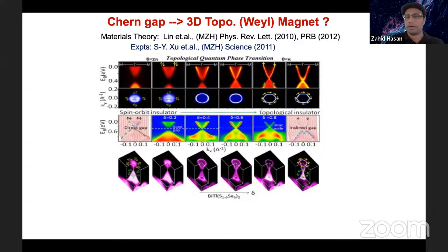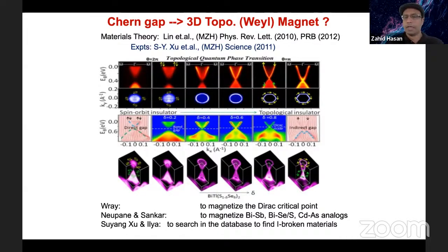So now that we know how to do a Chern gap or topological gap in magnets. Back in 2010-11, we were exploring a band inversion transition in a topological insulator. At the band inversion point, you have a 3D Dirac fermion, right? And when you magnetize a 3D Dirac fermion, as we know, it can only split into a pair of Weyl fermions. So we were trying to magnetize this Dirac critical point in a topological insulator system. But it turned out that magnetizing topological materials is a very tricky job. And even if you magnetize it, the gap may be small, ARPES may not be able to see it. So that was happening back then. We could not resolve the Weyl splitting. It's a resolution issue of ARPES.